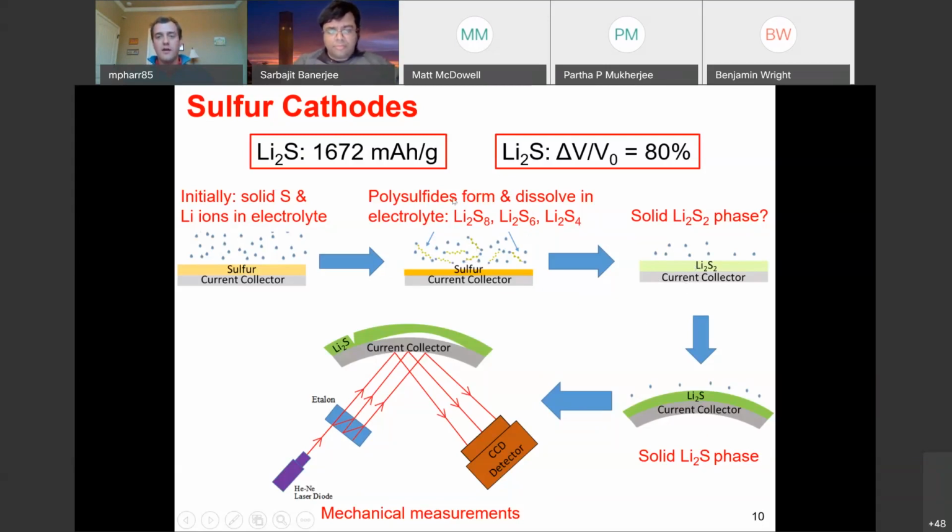And overall here, theoretically, from going from pure sulfur to Li2S, you get 80% change in volume. And so this is really large, and you may just think, okay, we're screwed here. What are we going to do? But remember that for some of these transformations, this is a solid becoming a liquid, so I no longer have stress to speak of. But then again, we deposit back as a solid. And if while we're in this solid state, we build up enough stress to drive, for instance, detachment from the current collector, then we've lopped off a big piece of this active material and it's electronically isolated and effectively dead. So we still have to be careful that during this whole process, we don't build up big enough stresses that drive damage in the solid state.